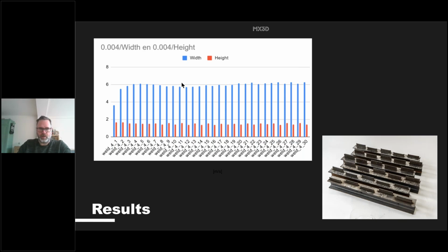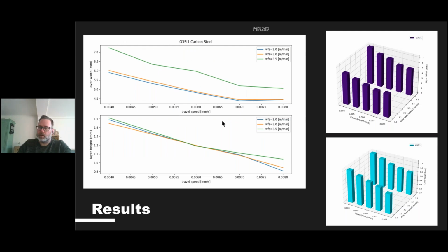So this picture is a carbon steel graph. When we aggregate all the data of, for example, the carbon steel, we come up with these pictures. What we can see here is that we varied the travel speed, and we did the experiment for 2 distinct wire feed speeds. And we repeated one of the processes to see the reproducibility. And as you can see, the 2 lines are matching pretty closely.